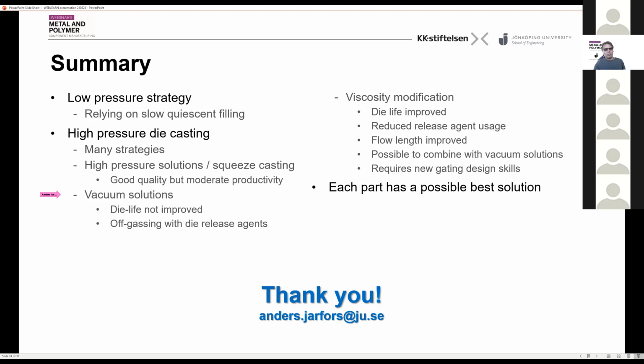You have vacuum solutions, and those give you very good quality, but you also have issues with die life because you still need to use the same type of die spray. You have off-gassing issues. If you use viscosity modification, you will get a die life improvement because you carry less heat into the die. Less heat into the die means that you can reduce your release agent usage, and that means that you have fewer issues with off-gassing during filling. And you can also fill longer if you're in the range 30 to 50%. And it's possible to combine this with vacuum solutions, but you would probably need a new gating design.